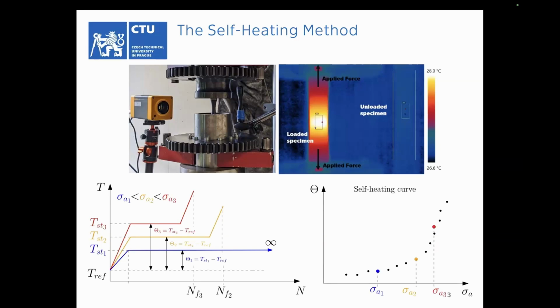If you do more measurements like this, you can take these stabilized temperature increases and plot them into this diagram, where you have stress amplitude on the horizontal axis and the temperature increases on the vertical axis. These points form what is called the self-heating curve. It usually has two regions differing a lot by their slope, and the fatigue limit is found somewhere in the transition between these two zones.